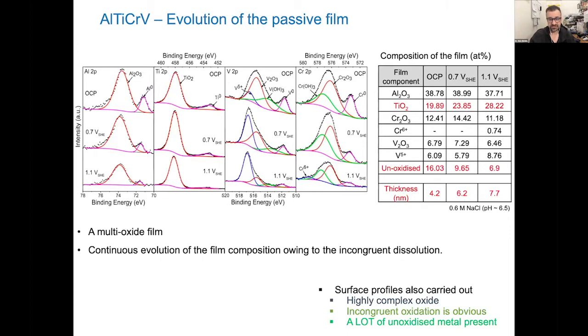So having unoxidized metal in a film, we think, is a significant characteristic of where these particular alloys get their corrosion resistance. It also turns out that the thickness of the film changes as you polarize it anodically, and you get a continuous evolution of the film composition. I'm not showing you sputtering XPS here, but these are highly complex oxides. The incongruent dissolution is obvious, and you have a lot of unoxidized metal present.